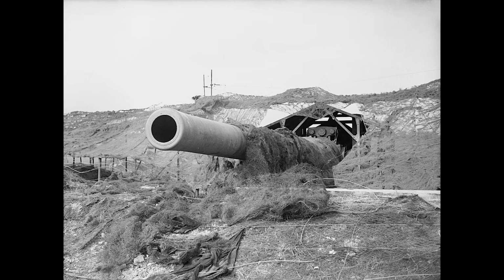catastrophic failure. When post-war testing revealed that British and German armor was approximately 20 to 25% more effective than American armor against large-caliber projectiles at typical battle ranges, the Navy's metallurgists had to confront an uncomfortable reality. American armor was optimized to break American projectiles, the strongest armor-piercing projectiles in the world. But in actual combat, American ships wouldn't be shooting at themselves. They'd be engaging Japanese or potentially German ships, protected by Japanese or German armor, and firing Japanese or German projectiles that weren't as strong as American shells.